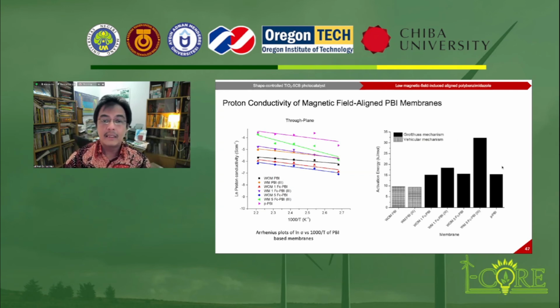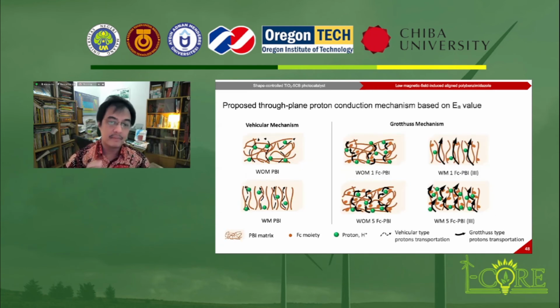Okay, and this shows the proposed proton conduction mechanism based on the Arrhenius plot of the polymer-based membrane. It is suggested that without the addition of the ferrocene moiety in the polymer matrix, the vehicular mechanism exists as the dominant transport mechanism of the membrane. This indicates that the proton conductivity is possibly contributed from the polymer matrix.